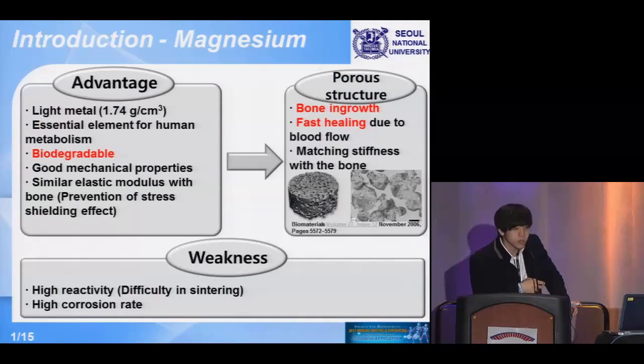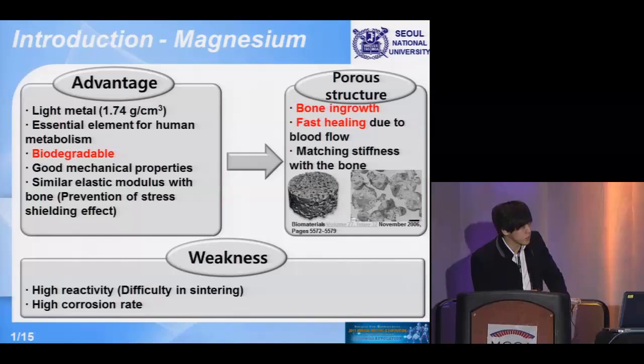But there are some weaknesses of this porous magnesium. First, one of the methods to make the porous structure is powder metallurgy. But because of the high reactivity of magnesium, the powder has an oxide film on the surface, so it acts as a barrier for the diffusion during sintering. And another, most big reason is that magnesium corrodes very fast. So in aqueous solution it is hard to use, and during the corrosion, the strength decreases and hydrogen gas evolution happens, which hinders the cell attachment.